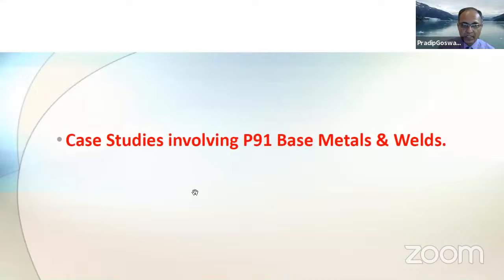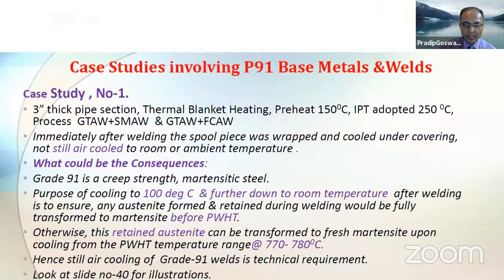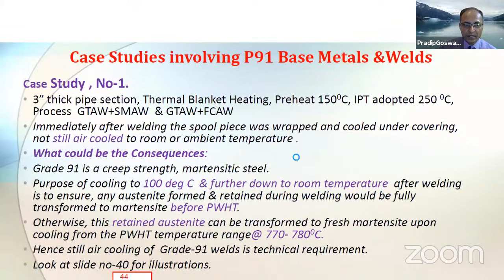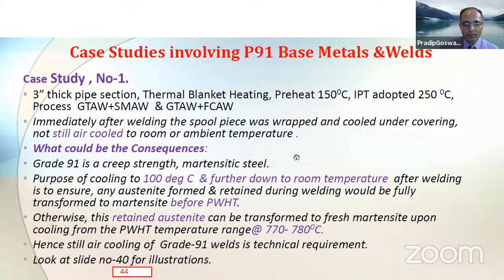In the next few slides, I have tried to cover a few case studies involving grade 91 base metals and welds. Case study number 1. It states a 3-inch pipe section under thermal blanket heating, preheated at 150 degrees centigrade, interpass is 250 degrees centigrade, process stick as well as TIG and flux core arc welding.